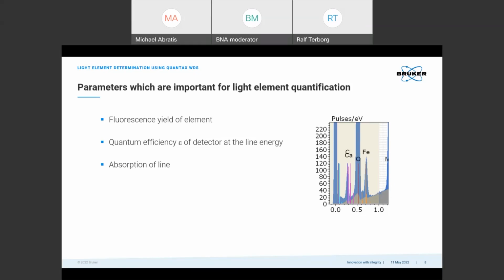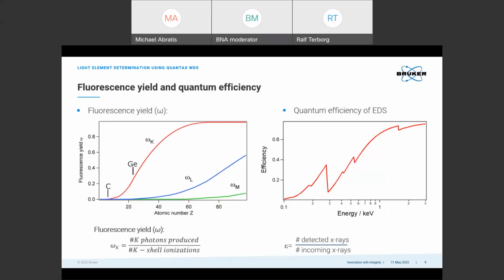This spectrum is an almandine garnet acquired with an accelerating voltage of 20 kV. And you can see, for example, high energy lines like the Fe K line at 6.4 keV, but also lines in the low energy range. This is typically defined for energies below 1 keV. And here in this example, you can see the K line of carbon from the coating of the sample, the K line of oxygen, and the L lines of calcium, manganese, and iron.